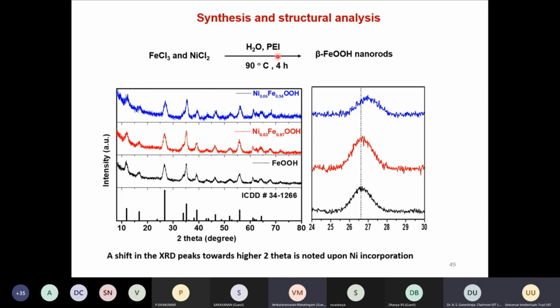Again, it's only 90 degrees centigrade for 4 hours. You get beta iron oxyhydroxide nanorods, which I'll show in the image. We first confirmed the phase of this material, which matches with the iron oxyhydroxide phase. And what we observed after nickel doping is a slight shift to higher 2 theta value.